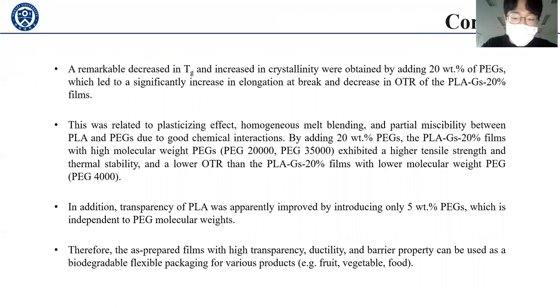And in addition, the transparency of PLA was apparently improved by introducing only 5% PEGs, which is independent of PEG molecular weight. Therefore, the as-prepared films with high transparency, ductility, and barrier property can be used as biodegradable, flexible packaging for various products.